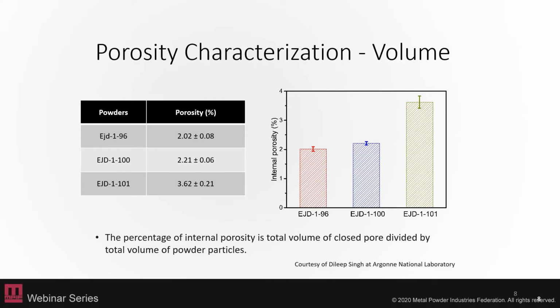Here he's characterized those samples and given the porosity percent as the total volume of closed pore divided by the total volume of the powder particles themselves that were present in the sample. It ranges from 2% up to almost 4% within these samples, and these were provided by the same commercial partner. So even just within batch to batch, you can get some variation of the internal porosity that will stick within your final powder produced part.